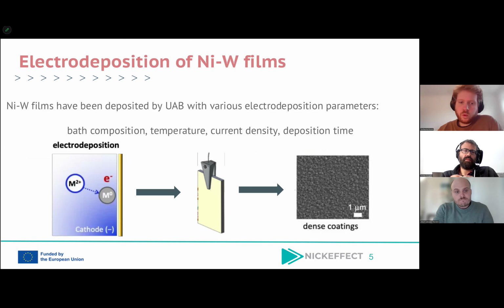There we had discussions with UAB, the University of Barcelona, and they were depositing nickel tungsten films using different electrodeposition parameters. They were using two different baths. They were trying different temperatures, different current densities, and different deposition times. So they had different nickel tungsten films, and we wanted to see if we could help improve the performances of the films by tuning these parameters.